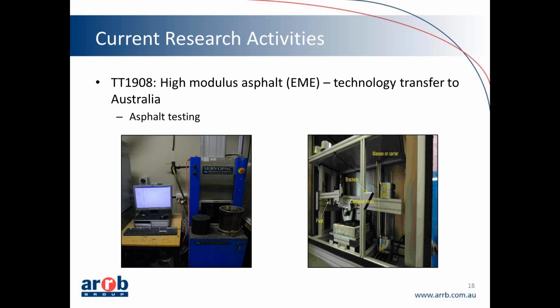The main variation to the EME we were tracking compared to what we would do as standard in Australia is that the test usually runs for around about 10,000 cycles or 4 hours. For the EME, it was important to do it at 60,000 cycles, which is 24 hours. So that test was running for quite a long period of time.